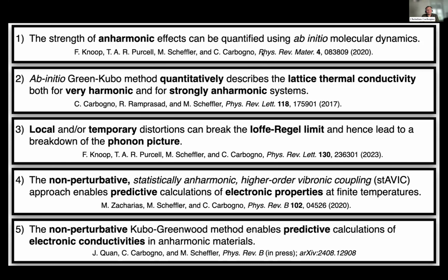But what this exploration has shown is that already at 700 K, many materials become quite anharmonic. So I would say at 2000 K, if you don't have a particularly special material, I'm pretty sure that it will be strongly anharmonic at 2000 K. And harmonic behavior would be rather exceptional.